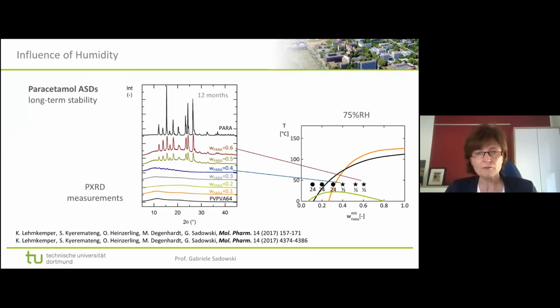And this is to show how we find the crystals. This is not just that we look at the samples, but we make XRD measurements, and then you see this is a pure polymer, and very much on the top is pure paracetamol in this case, and then you have the samples in between. What you see is that, for example, for this one, this is the 0.4 sample, this is the XRD measurement after 12 months, and you see these very little XRD peaks here saying we do see crystals here, but we don't see crystals at 0.3. And this is how we measure those samples and detect crystals besides DSC measurements. This is also what we do on top.